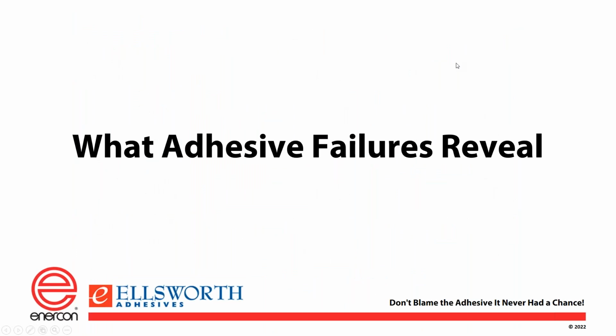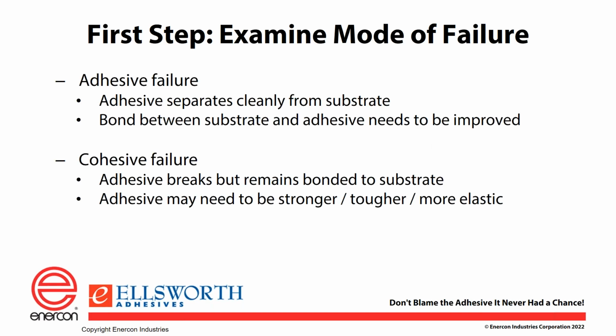So moving on to what adhesive failures reveal. Your first step is to examine the mode of failure. And you may remember from a previous slide, we have two main modes of failure: adhesive failure and cohesive failure. The adhesive failure, the adhesive will separate cleanly from the substrate. So the adhesive itself is intact, but it is no longer stuck to the thing that you tried to glue it to. In that case, the bond between the substrate and the adhesive needs to be improved. For cohesive failure, the adhesive itself breaks apart, but it does remain bonded to the substrate. In that case, the adhesive type may need to be changed. So it may need to be chosen to be stronger or tougher or more elastic, depending on how much strength you need in that bond.